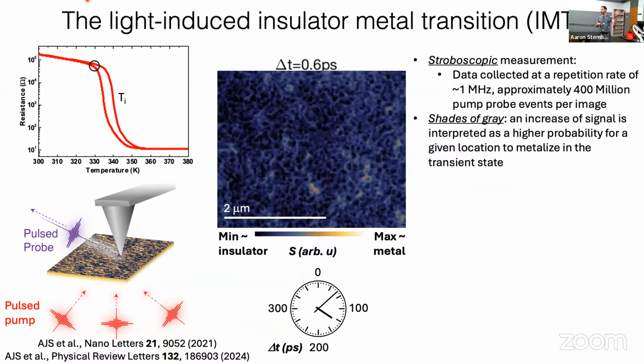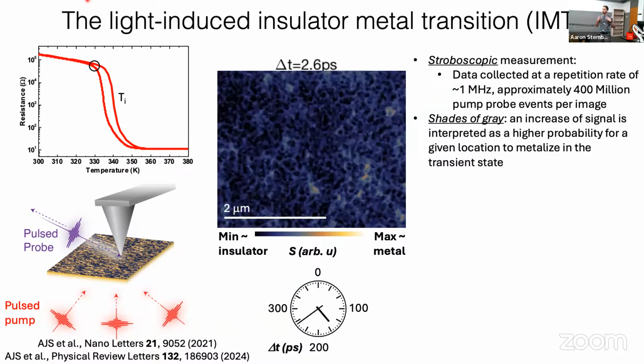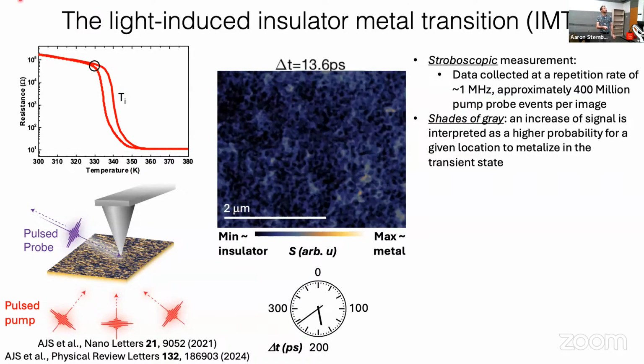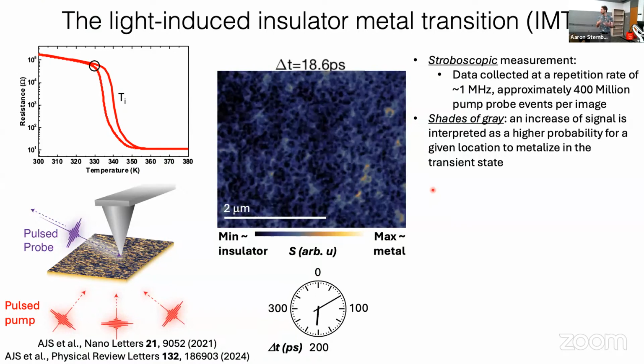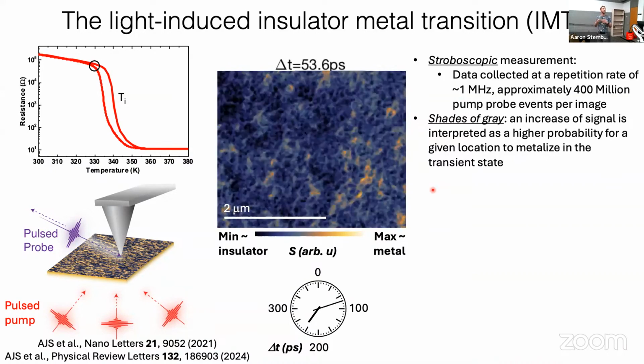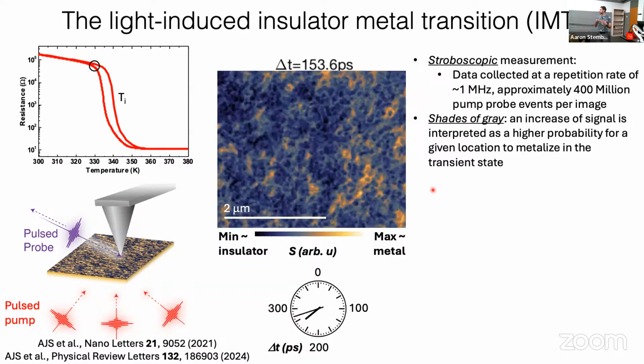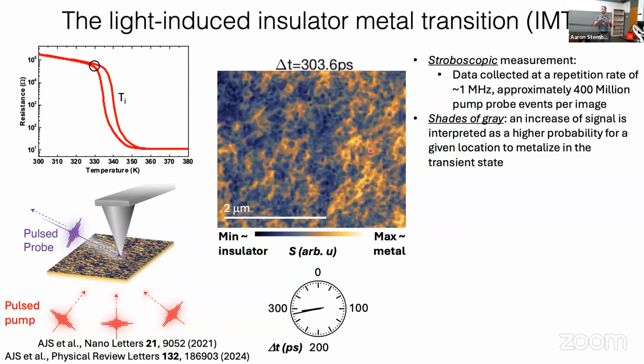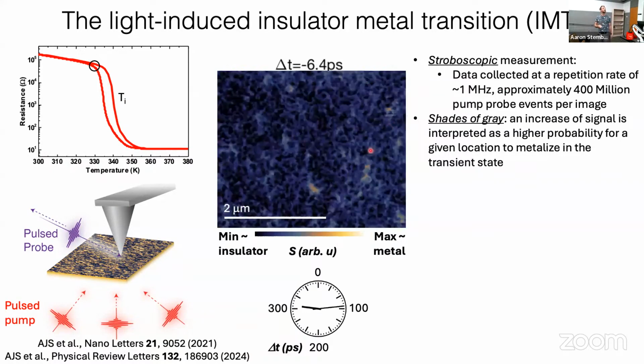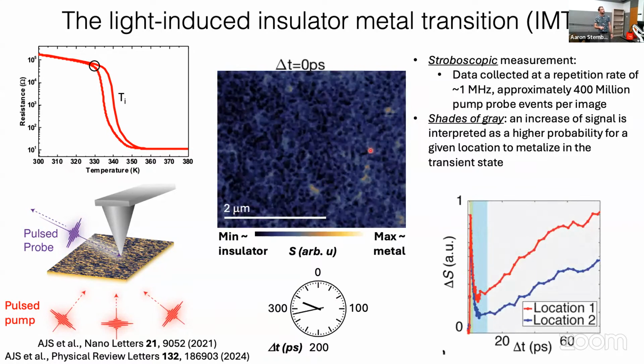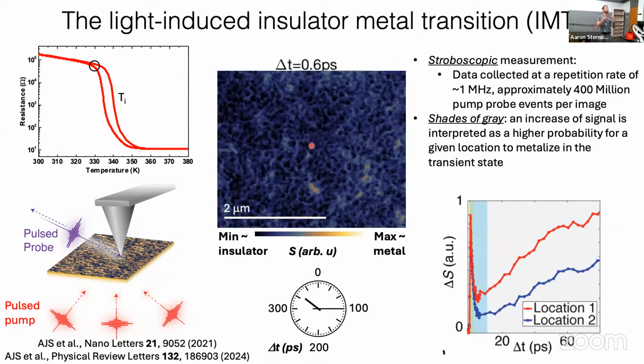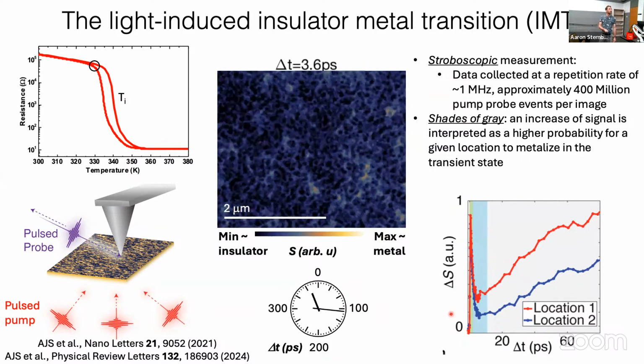And so the only thing that we can see are regions that reproducibly become more metallic at a given location. So you should think about an increase of signal as suggesting that the probability for a given location to become metallic at a given time delay is higher. Okay, it is not necessarily going to tell you the exact single shot conductivity in a given pump probe event. Nonetheless, we can use this measurement to learn about how the system evolves from an insulator to metal.